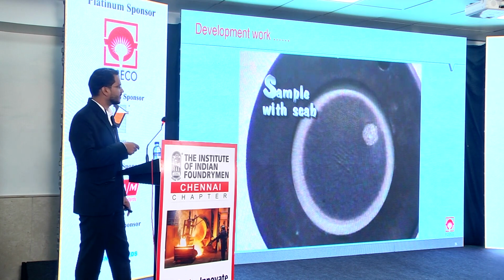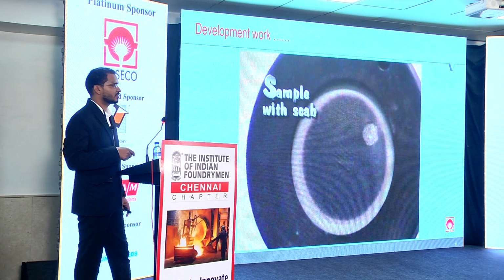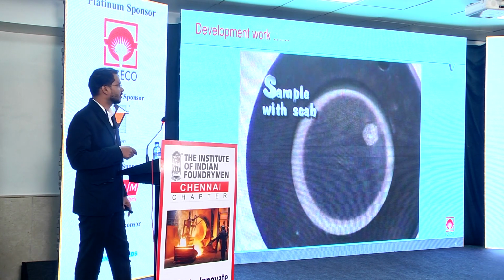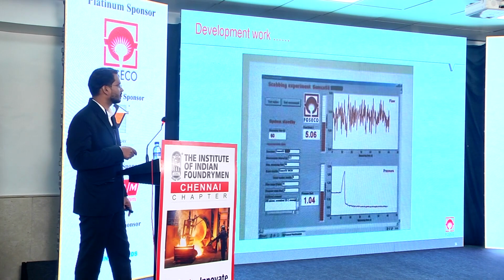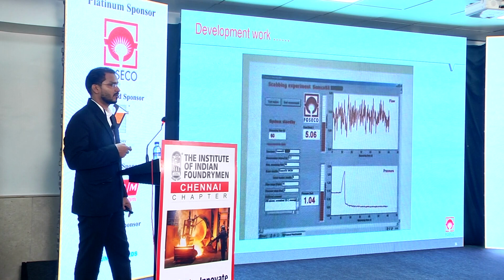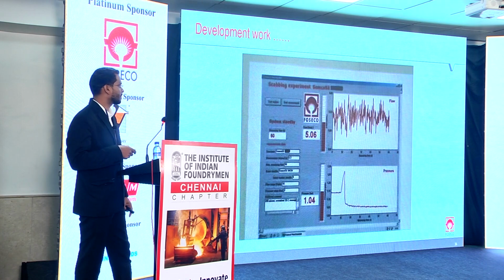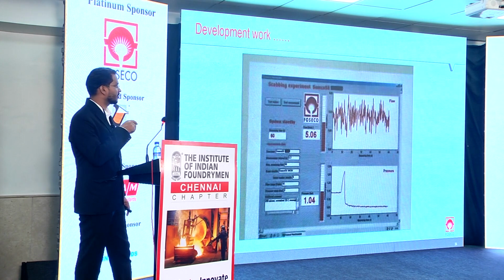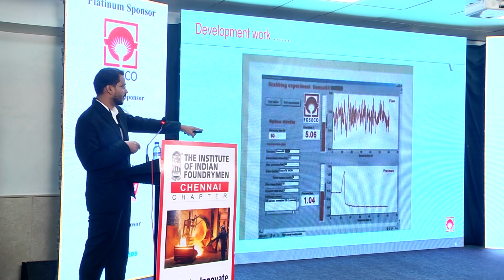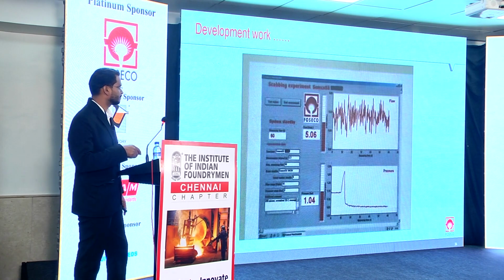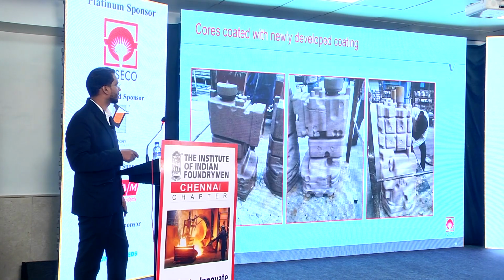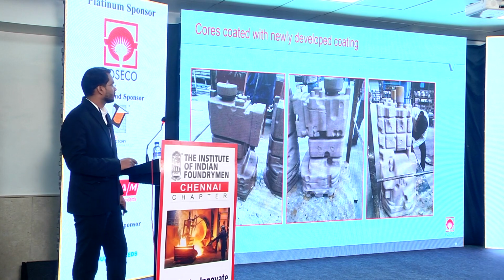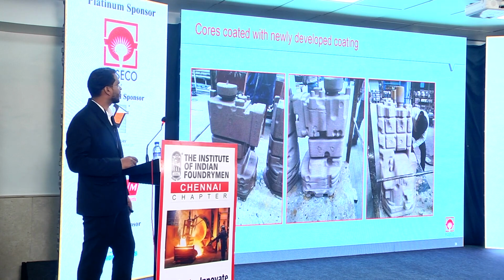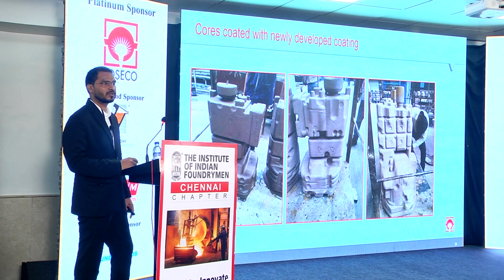So that is what we tested, different coatings after our developments, and then we found one of the coatings started working perfectly, and then we took it to the foundries and tested it. From this test also you can see with continuous flow, after this puncture the pressure is reduced. So these are the housing castings coated with the newly developed coating.